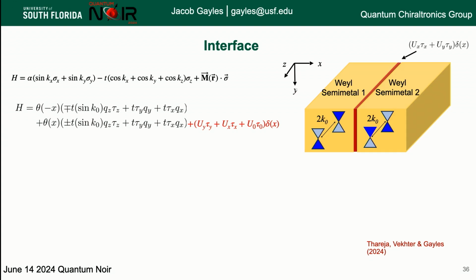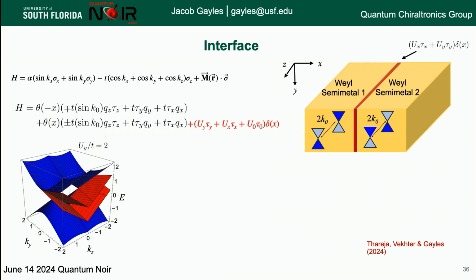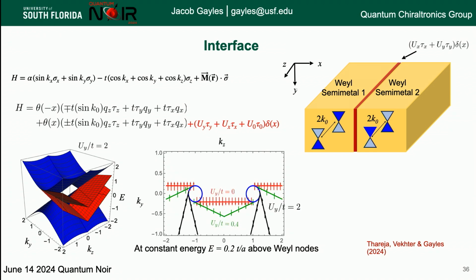We change the chirality of these Weyls. We have one here and a different one here. And what we see is that this blue curve here is that Weyl dispersion that we had before. But what we get new is, at this interface, we get these bound states. And these bound states are topological, meaning that they're very hard to destroy. And we get two of them there. So I'll let you think about why that's interesting, because they also have some spin characteristics. That's the plane cut of these states that we have. So that's the Weyls here, and then they connect throughout the Brillouin zone there.